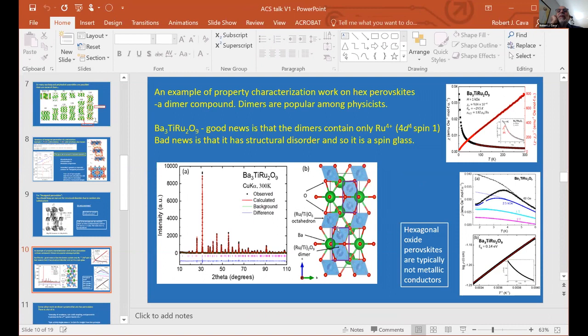So this is Ba3TiRu2O9. And nominally, you would guess that the titanium is separated from the ruthenium so that the ruthenium make these dimers and the titanium is separate. But that doesn't happen. What actually happens is that titanium and ruthenium are so similar that they have a disordered structure. And so you get what's called a spin glass,